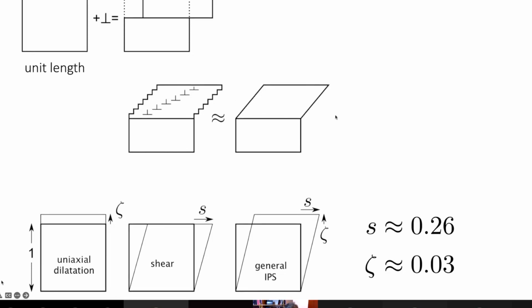And the nature of the shape change is not actually shear. So a shear would not accomplish a volume change. We need to combine the shear with a uniaxial dilatation like this, and that would give us what we call an invariant plane strain, which leaves this plane completely undistorted and unrotated, a coherent plane. And typically in steels, the shear strain is 0.26. Now that is huge, okay?